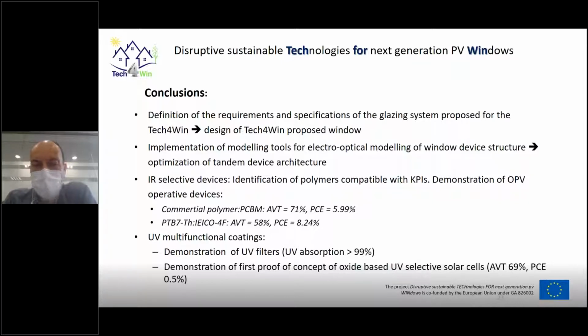In any case, what is important is that these results are obtained without the internal back reflector implemented. With the implementation of the internal back reflector, we expect a relative improvement in efficiency of about 20%. So this would allow, in the case of the higher transparency approach with 71% transparency, to recover and reach the 7.5% efficiency that is targeted in the project.